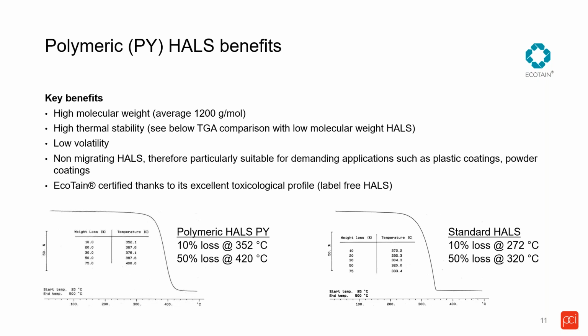This type of HALS actually is label free, which means that when we look at the SDS and compare it to a standard HALS used in powder coatings applications, what you will find is product not labeled at all. And that's really quite an advantage when you have an additive that allows you to formulate a powder coating without any toxicological profile, and that will enhance not only the performance, because again, polymeric HALS will last longer, there will be less loss during the curing of the coatings, but also provide you the advantage of the labeling.